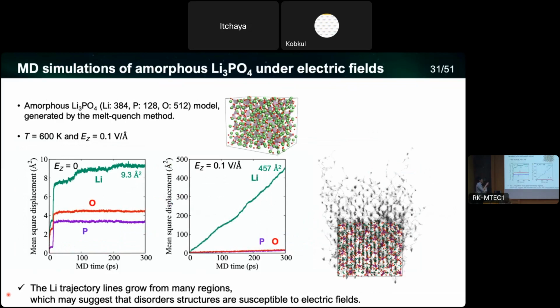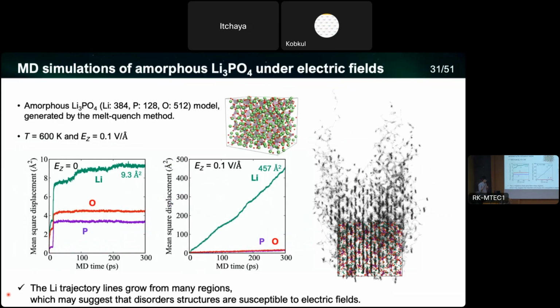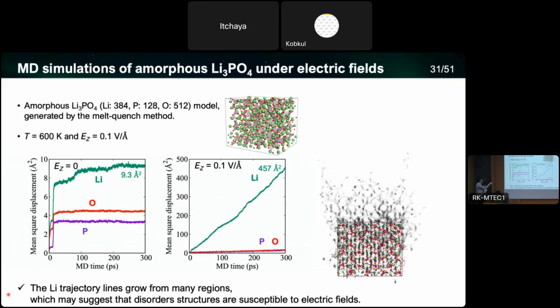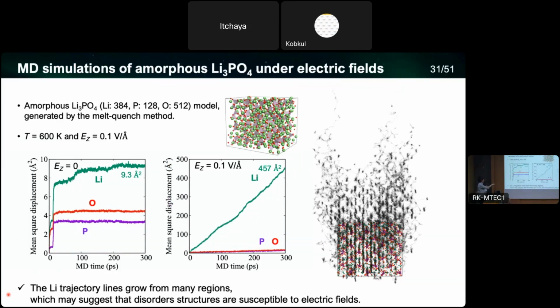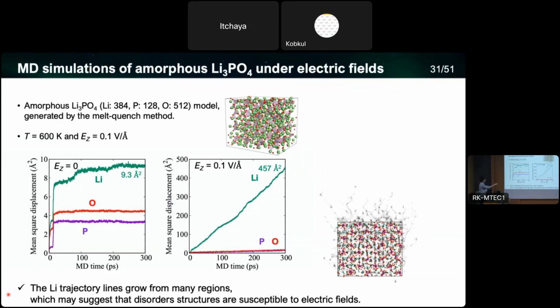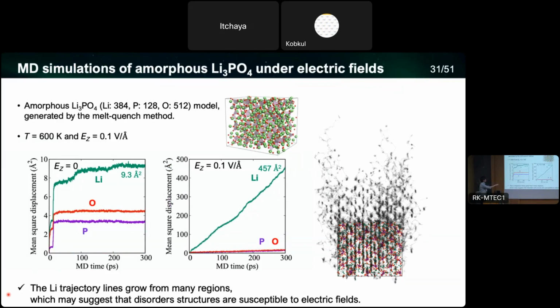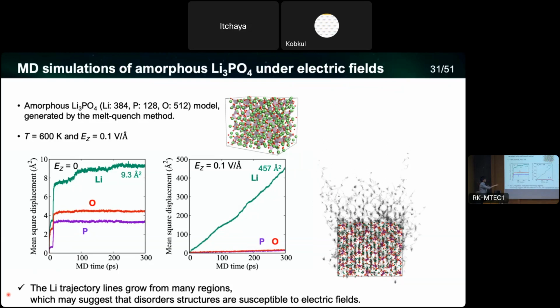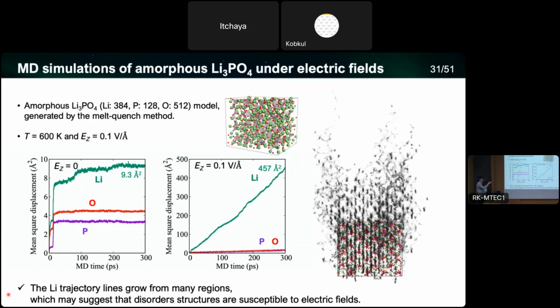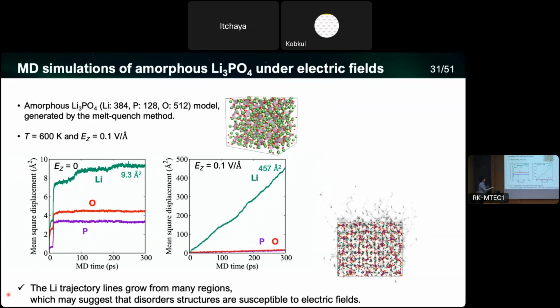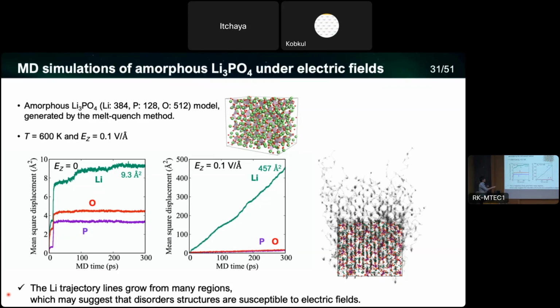And finally, we apply the same potential to the amorphous structures. In this case, we have no specific defects, so the number of atoms is the same as stoichiometric. This one is, again, the mean square displacement without the electric field, and the graph in the middle is under the electric field. As you can see, the mean square displacement drastically increased in the amorphous case. The increment is much larger than in the crystalline case. This is actually a surprising result.